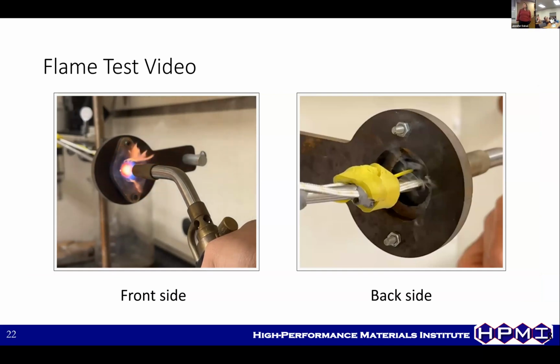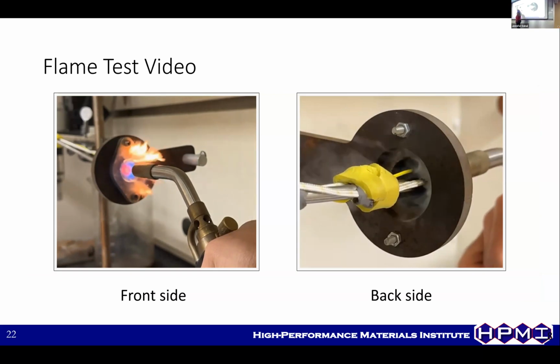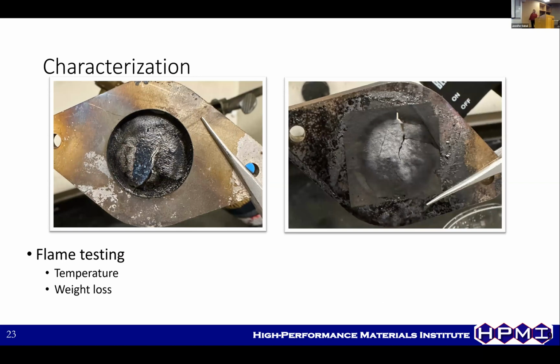You can see here's the front side temperature. We're clearly burning the surface. This frame was made to control where the damage was made. You can see that we have some smoking on the back side. We have flames on the front side, and so, if you guys were asleep at this point, here's some fire. And then we did some characterization and studied the temperature and weight loss before, during and after this test, and then looked at it under SEM to see what kind of things we got from there.